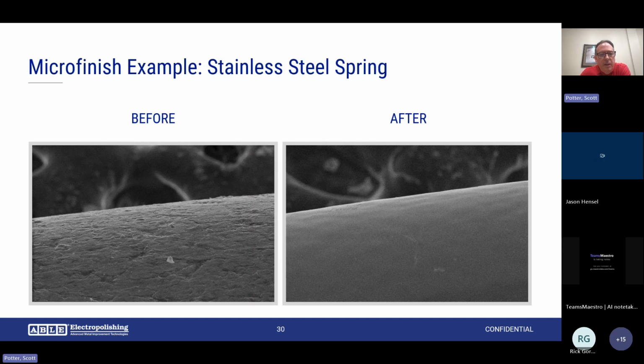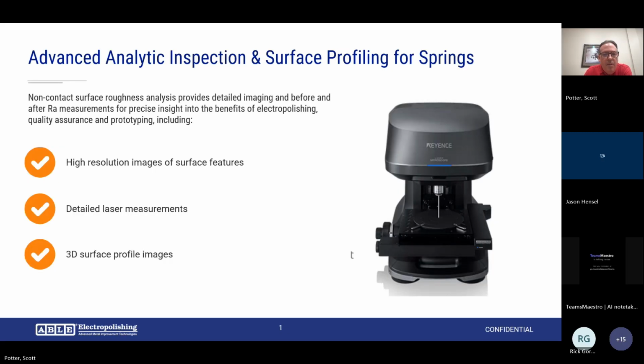Here's a stainless steel spring. You can see the improvement too. And typically, whenever we have a part like a spring where it's difficult to use a standard stylus profilometer, we'll use a laser microscope that we can use to get really accurate Ra readings before and after electropolishing. It can also get very accurate dimensional readings as well.